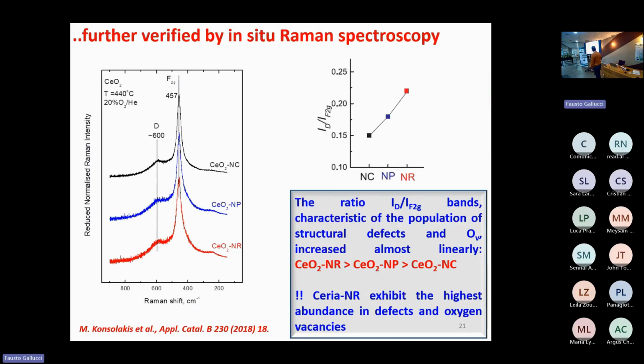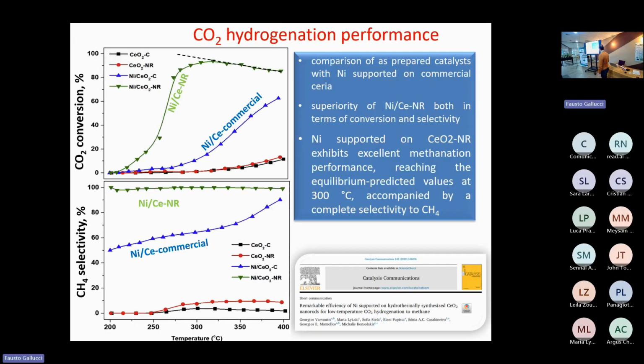And this is further verified by in situ Raman spectroscopy, which clearly reveals that the ratio of D to F2g band, which is indicative of the population of structural defects and oxygen vacancies, follows this trend: nanocubes, nanopolyhedra, and nanorods. Overall, nanorods exhibit the highest abundance in defects and oxygen vacancies.